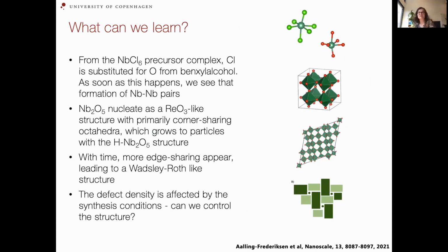So that's the kind of thing that we can learn from an experiment like this: from the niobium chloride 6 precursor, we can substitute chloride with oxygen from the benzyl alcohol, and as soon as this happens we see the formation of these niobium-niobium pairs.